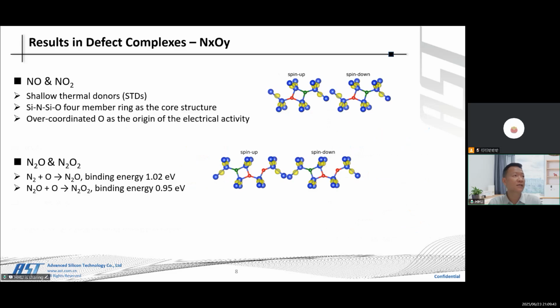Complexes such as the NO complex, NO or NO2, are shallow thermal donors. The silicon-nitrogen-silicon-oxygen four-member rings are the core structures. The over-coordinated O is the origin of the electrical activities. Then there are N2O and N2O2. N2O's binding energy is 1.02 eV, and N2O2's binding energy is 0.95 eV.